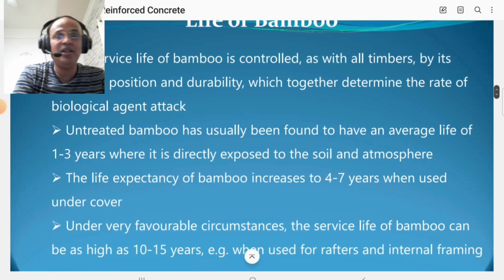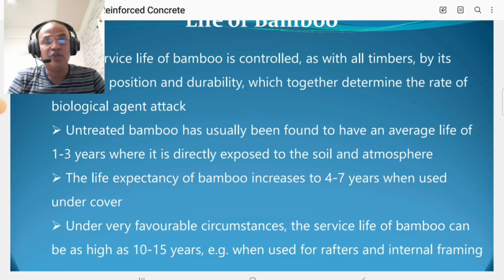So it becomes twice that of normal condition. And under very favorable circumstances, the service life of the bamboo can be 10 to 15 years when it is used as rafters or internal framing. But recent study in Brazil and other countries showed that it can be used for high-rise buildings also up to a height of 200 meters, and that bamboo should be used with different coating material for the adherence and to improve the other properties of the bamboo reinforced concrete. So that is very, very important for you people.